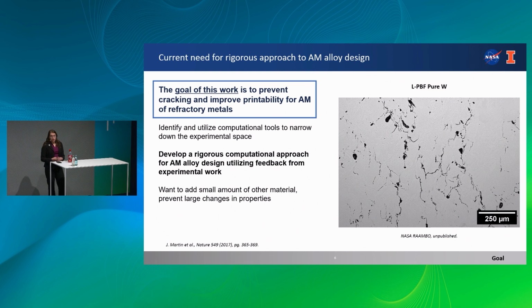As a result, you can end up having different compounds formed and get cellular structures, which tend to be very brittle and can actually be detrimental to your properties. So with this, the goal of our work is to really prevent cracking and improve printability of additively manufactured refractory metals. And we want to identify and utilize specific computational tools that can help us do this. Like I said, we want to develop a rigorous approach to designing these materials and determining what effects these nanoparticles will have. And as I previously mentioned, we want to add as little additional material as possible so we can retain those properties but help prevent cracking and actually improve mechanical properties.